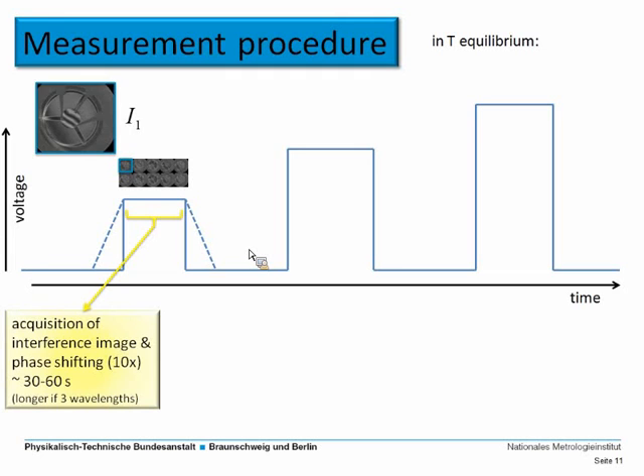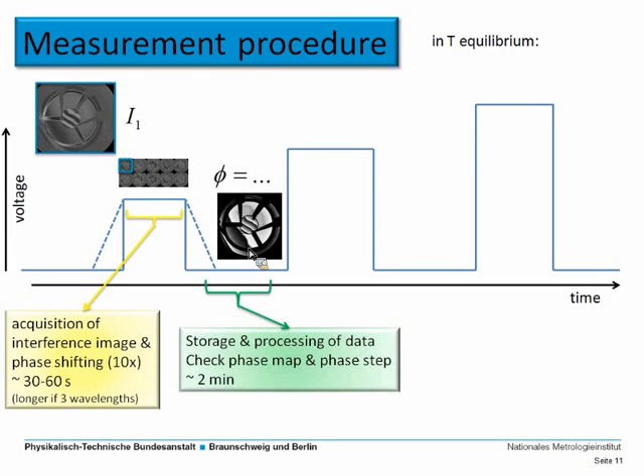Remember, due to this phase shifting technique, we have to acquire more than one image. In this case, it's 10 images for the algorithm we're using. This takes about 30 to 60 seconds, and longer if we are using 3 different wavelengths for the absolute length measurement.